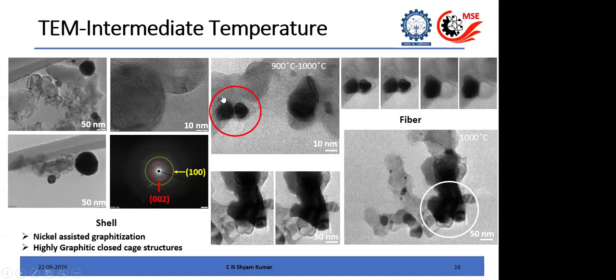So you can see that these black particles are nickel particles, which are coming together, and also it is graphitizing while it is moving. So this part is kind of amorphous carbon, and this part is graphitic. These layers are graphitic carbon, and here you can see the black part is receding, and the highly graphitic layered structure is being formed here. So now we know that the nickel is moving and coalescing, and in that path, it is being graphitized.